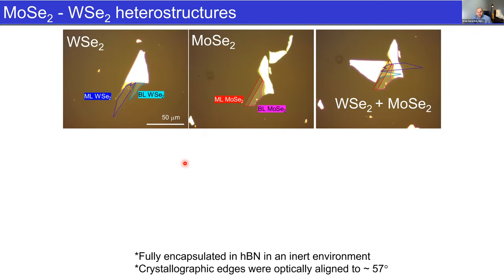The sample that I'll be talking about today, actually everything I'll talk about today, comes from one sample that has been kept in a cryostat cold while we've been on lockdown, trying to measure remotely. The heterostructure is a tungsten diselenide and molybdenum diselenide heterostructure. You can see here an optical micrograph, with a monolayer region of the tungsten diselenide and also a bilayer region, and similarly for the molybdenum diselenide. Based on the straight edges, they cleave along preferred edges when you do mechanical exfoliation. We can then combine them with a certain twist angle. In this case, we can work out optically that the twist angle is about 3 degrees, and we confirm that with various other approaches as well.